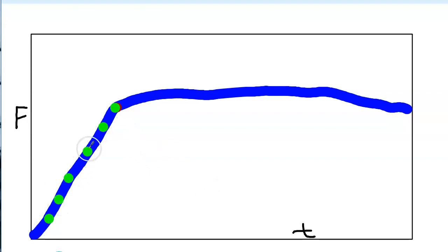So you can pick any force along this line. Pay attention to the deflection line. It should be a uniform, slowly rising line. If it's got flat spots in it, that means somebody stopped or slowed down. If it's got a curve in it, they're speeding up. So keep that in mind. Some of the samples are not real clean, okay?